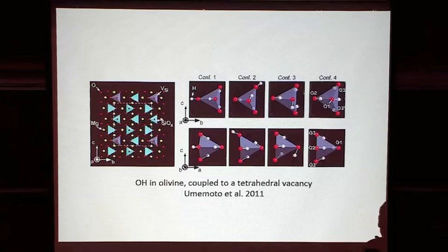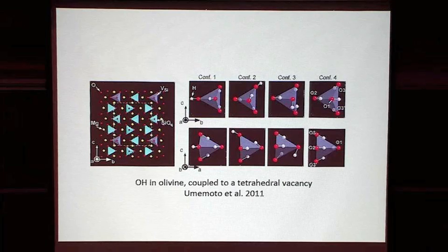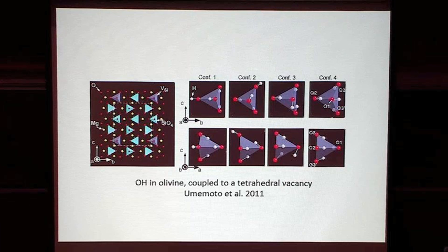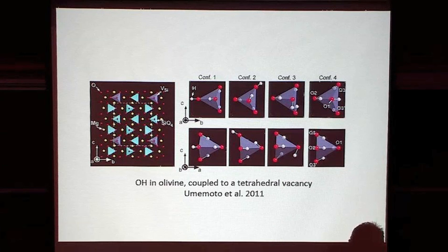So a really great example of that is what I was talking about before, about the weakness of hydrated olivine. This is actually the result of a first principles calculation that I was involved in, although I didn't do the calculation, trying to locate the hydrogen or hydroxyls in olivine. And what you can see is a number of different configurations. They are all surrounding a tetrahedron in which there is a silicon vacancy, right? The hydroxyls are coupled to vacancies. They may be coupled to tetrahedral vacancies, they may be coupled to octahedral vacancies, but the reason that hydrogen weakens olivine so much is that the hydroxyl simply wouldn't be there if it weren't coupled to the vacancy. And it's in fact the vacancy that allows for greater diffusivity, lower viscosity, and so on.